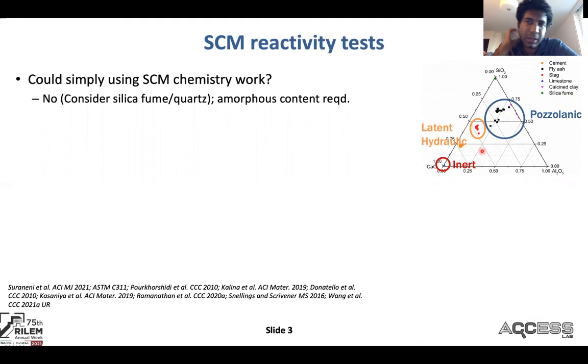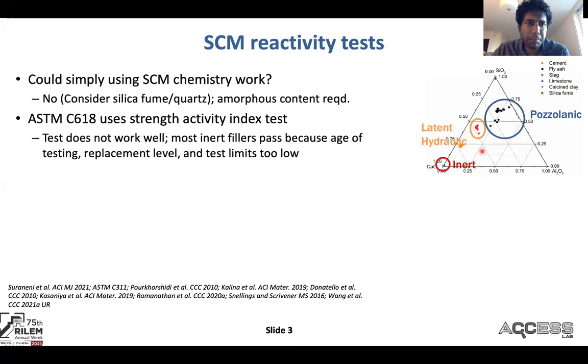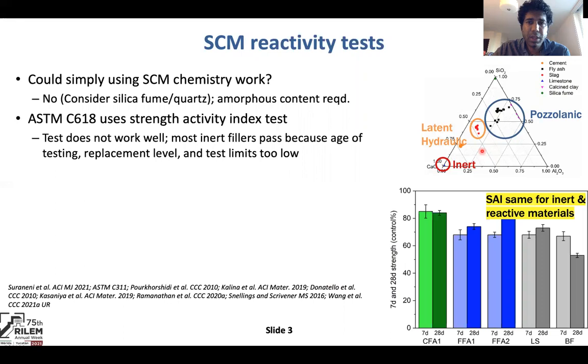You'll see a lot of papers in literature which say that something has more than 70% of S+A+F, therefore it must be reactive, but that really doesn't mean anything at all. The ASTM C618 strength activity index test is unfortunately a pretty terrible test — it's really not measuring anything to do with reactivity; it's measuring a filler effect because the age of testing is very early and the replacement level and test limits are simply too low.